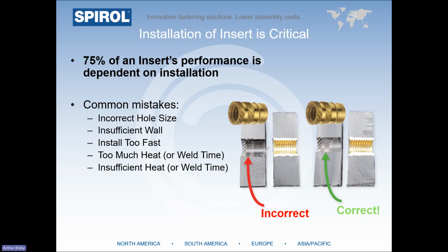After the insert is removed from the plastic, a mirror image of the insert's features should be present in the plastic. As you can see in the incorrect example on the left, the knurl's imprint of the plastic is very shallow, and there doesn't look to be any evidence that the barb actually engaged with the plastic at all. Also worth noting, there shouldn't be any voids present between the insert and the plastic.